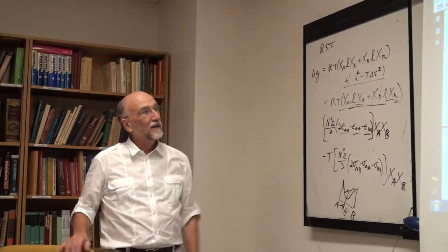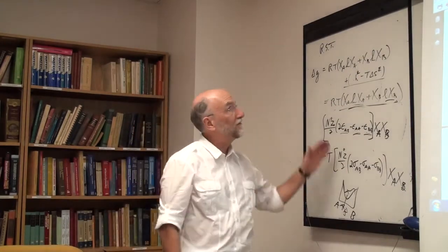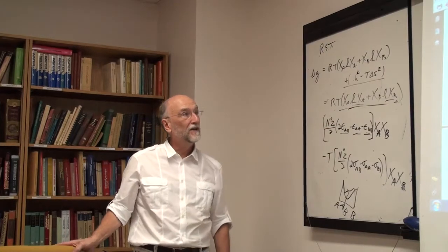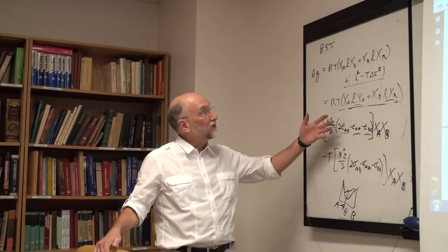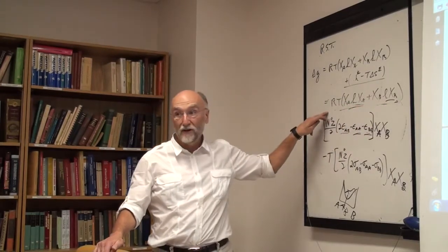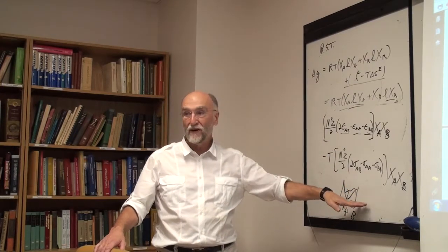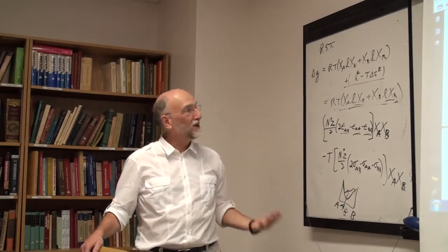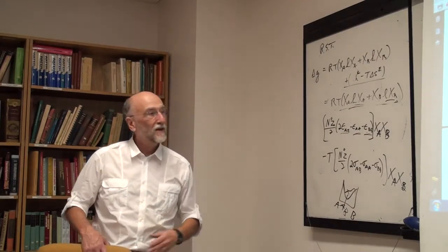So the regular solution theory polynomial, and people unfortunately use polynomials when you have very large deviations from ideality. When you have small deviations from ideal mixing, then like in the regular solution theory, the ideal mixing term is probably pretty good. Unless, of course, you're talking about salts like sodium chloride, potassium fluoride, then even if it's close to ideal, it's not good because you haven't taken account of what the actual dissociation is.